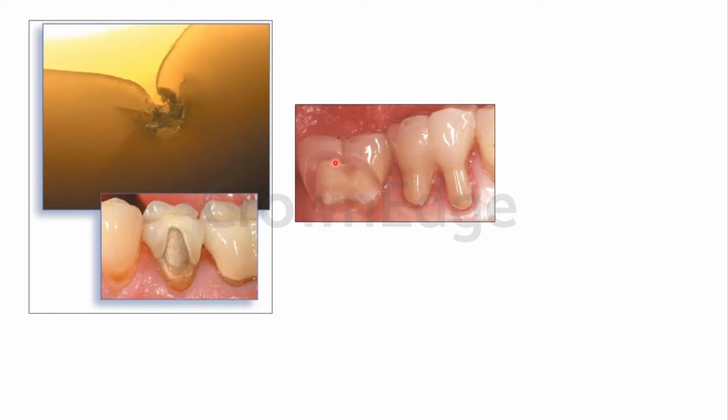What happens is that when you leave your tooth preparation nice and sharp, the ceramist is not able to put a large bulk of porcelain in that particular area. So that porcelain, as you know, is a very fragile material, just like glass. If you have increased bulk of the porcelain, that much more strength is present. Okay, it becomes stronger. So if you put a sharp line angle in your preparation, or the ceramist puts a very minimal amount of thickness of porcelain, it will definitely chip or crack. So that is what has to be kept in mind.